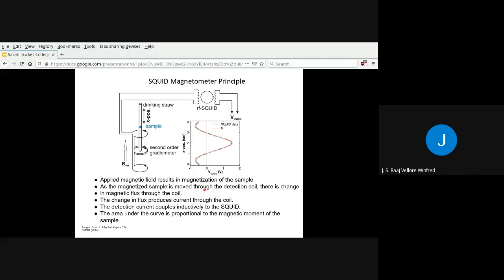Okay, so this diagram briefly shows what's happening in a SQUID. We apply a very strong magnetic field. This magnetic field would magnetize a sample. The sample is basically kept in just a normal drinking straw, because a normal drinking straw is not magnetized when you apply this magnetic field. The sample is then moved up and down through this coil that you see over here. The applied magnetic field results in the magnetization of the sample, and this magnetization would itself give out its own magnetic field.